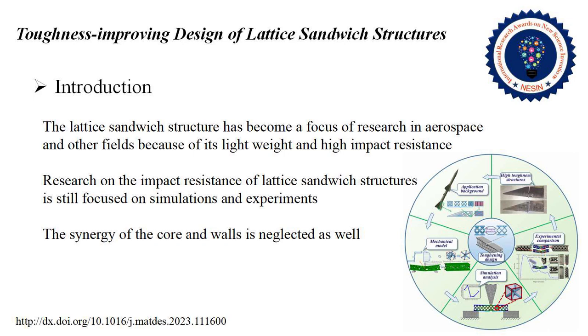In addition, the key technology of toughness-driven design has also made a breakthrough in recent years. When under a dynamic load, the mechanical behavior of lattice structures will depend on the strain rate. Its deformation mode and failure mechanism will also be changed by the strain rate. Some researchers noted that the strength and energy absorption capacities of lattices improved with increasing strain rate at the stage of low velocity impacts. When the strain rate is further increased, the inertia effect should be added. Over the years, researchers have also carried out much work in the research directions of low-velocity impacts and explosions to explore the mechanical responses of lattice structures under dynamic loads.